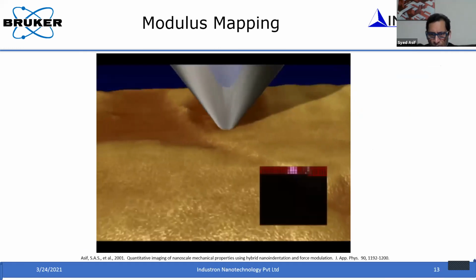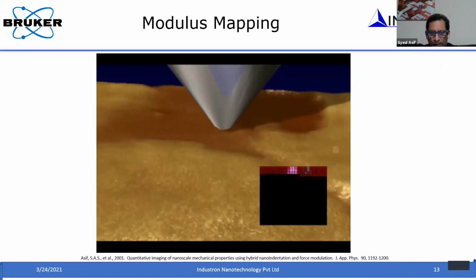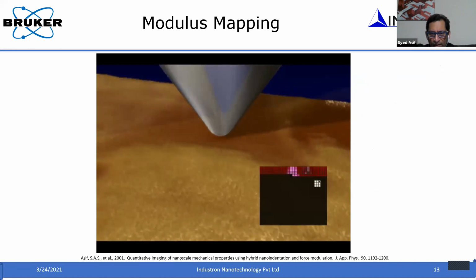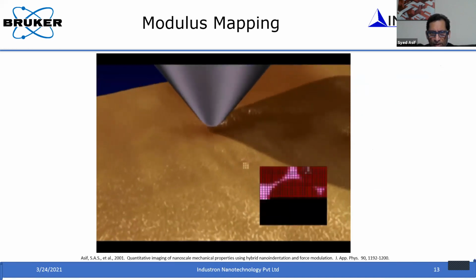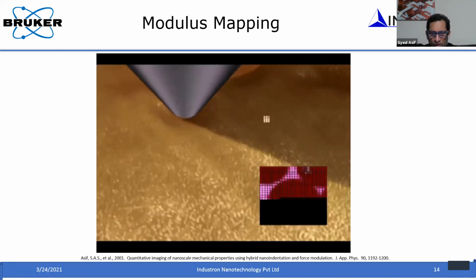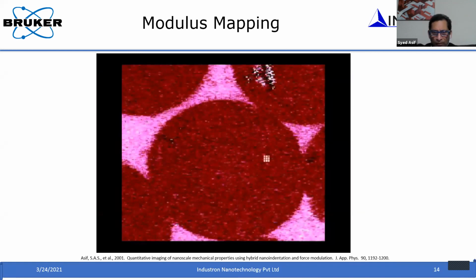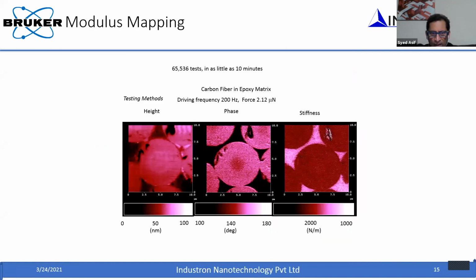So I'm showing this in a cartoon video, where you can see that you scan on the surface, at the same time oscillate, and then measure the response. Basically, you measure the stiffness response as you do that, and then line by line you construct the response. As you can see here, for example, in in situ SPM imaging, you measure the topography. Along with the DMA, you can also see the phase shift between the force and the displacement in image format, and also the stiffness in image format. This is for a fiber epoxy composite. You can see immediately the contrast in the image: the central region is a fiber, and then you can see the epoxy region.